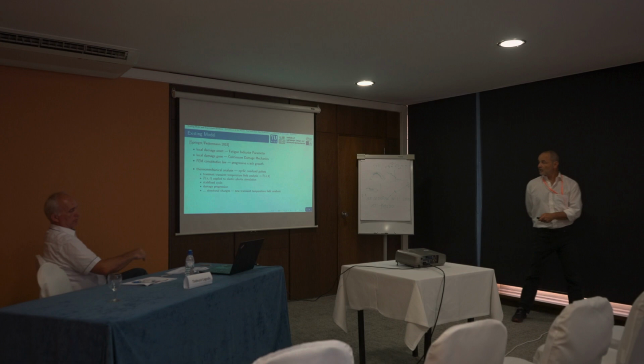So what we typically do, we run a thermomechanical analysis representing this overload pulse. So we start by a transient temperature field analysis where we have heat sources and heat conduction, and from this we get a temperature field which depends on the location and on the time. So it's a pulsating field, and this temperature field is the input to an elastoplastic simulation. We look for a stabilized cycle in our elastic plastic finite element simulation, and from this we can predict the damage progression. And since damage progresses, the structure changes, so we have a new structure more or less, and we have to go back to the temperature field analysis again and do this again, so we can loop through the damage progression.